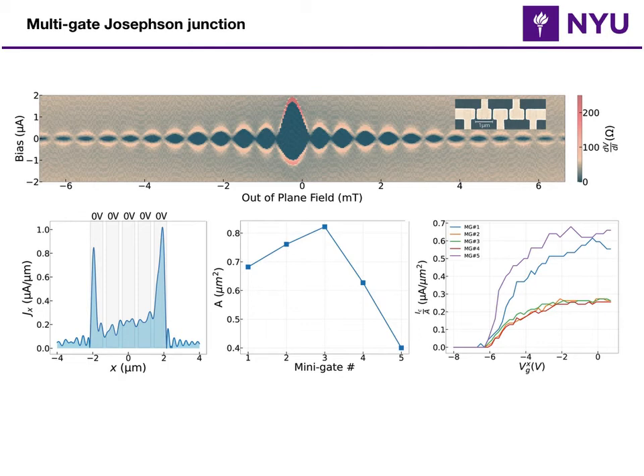Which is shown on the lower right. And you see that, surprisingly, there are 2 peaks at the ends of this current distribution, and there is some uniform current in the middle. If you look at the data, you can actually see why this is happening. The first node, while it seems to be closing, if you look at the data, there is a gap. And that gap suggests that the current is accumulating near the edges of the Josephson junction, not uniformly distributed.